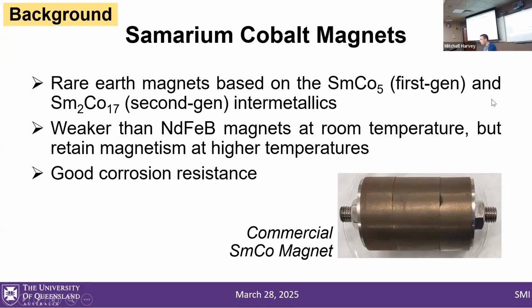In addition to working at better temperatures, samarium cobalt magnets have better corrosion resistance than neodymium iron boron. So most neodymium magnets that you see have either a nickel coating or a polymer coating. And if they get abraded or chipped or anything, they're going to start to degrade.